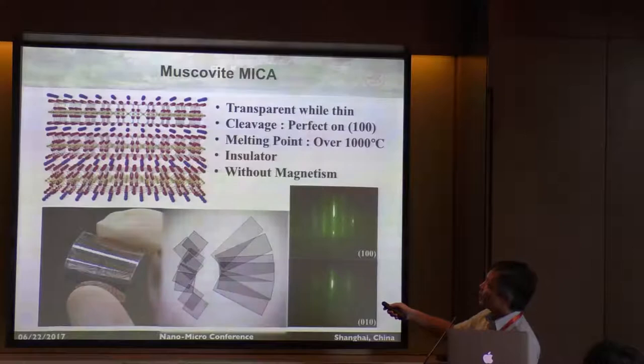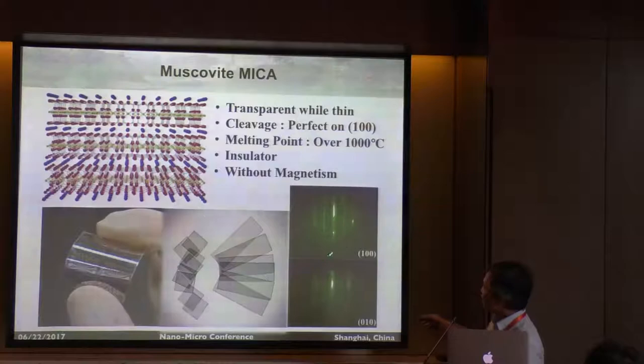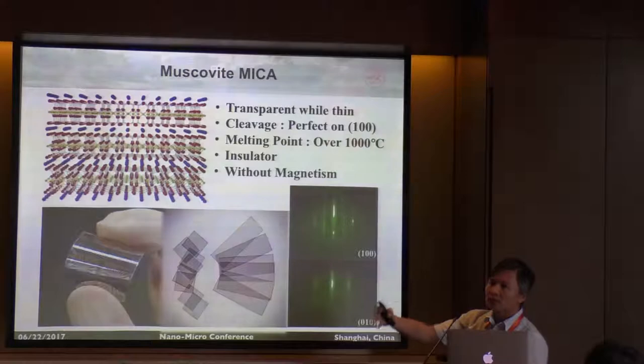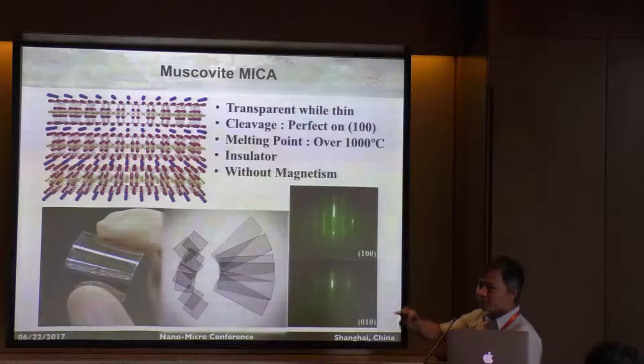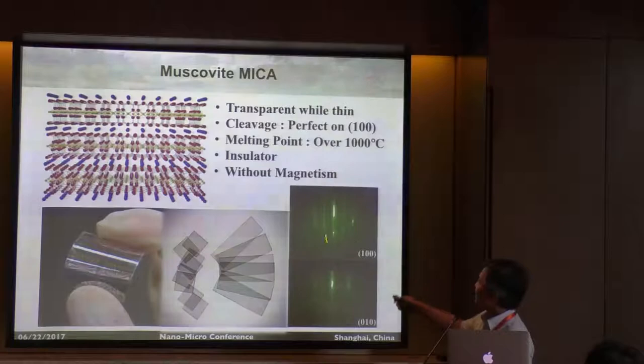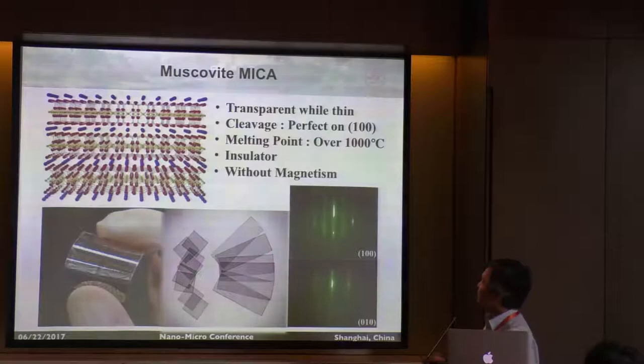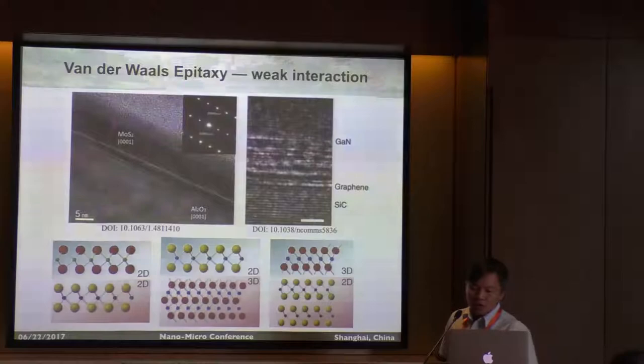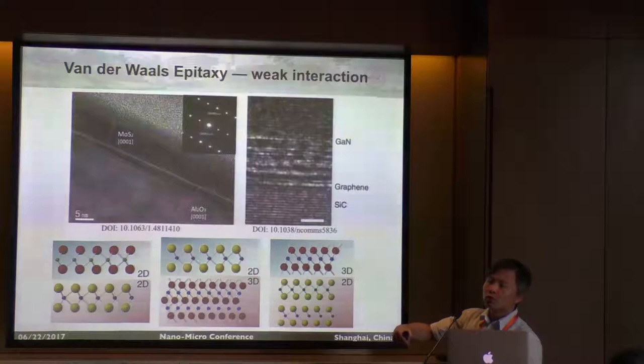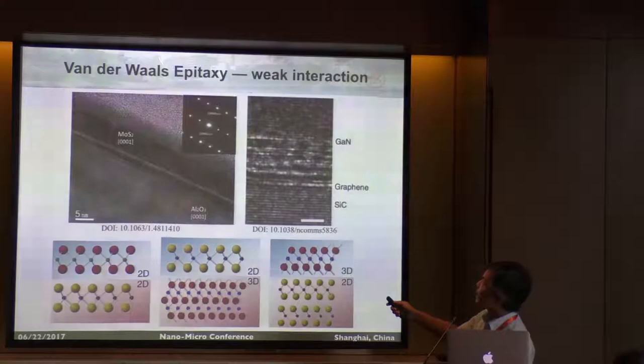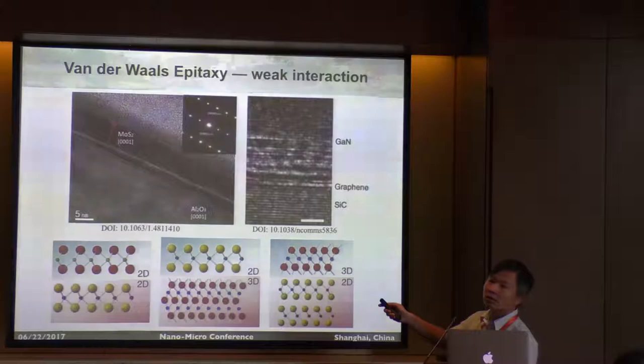We spent some time learning how to engineer the surface of muscovite. If you check the RHEED pattern, this shows the surface of your substrate. If the surface is not very smooth, you will see spotty-like patterns or no pattern at all. Every time we see a streaky-like pattern, that means your surface is very flat. That means you can use muscovite for epitaxial deposition.